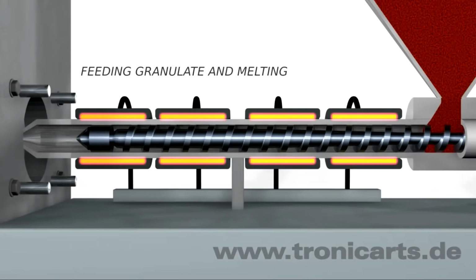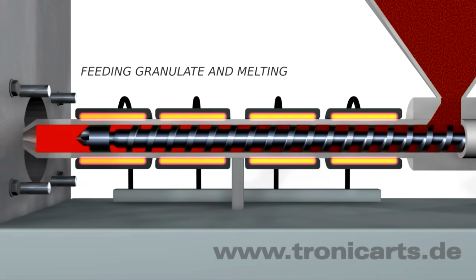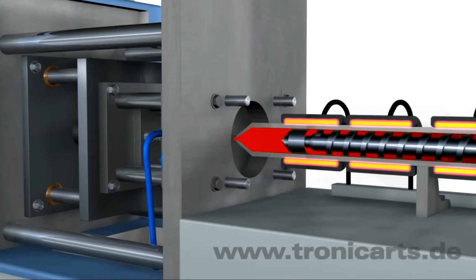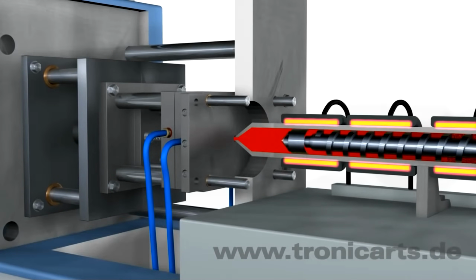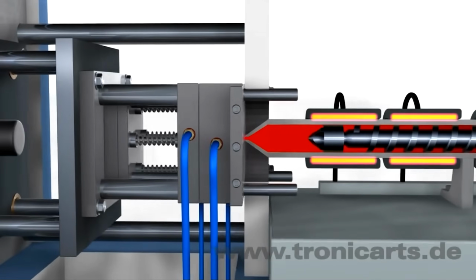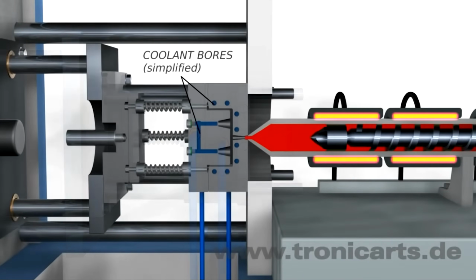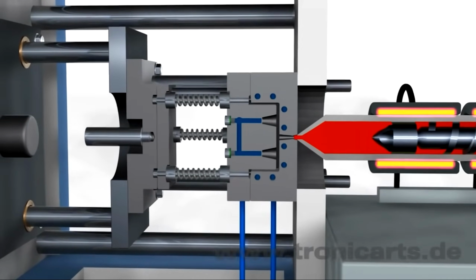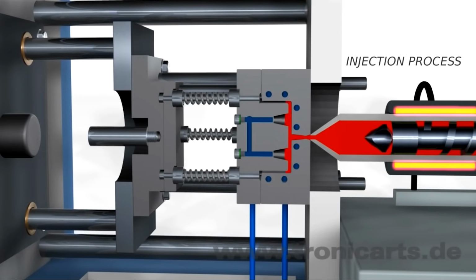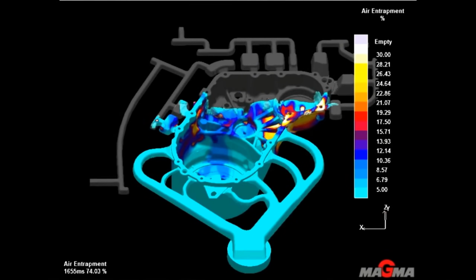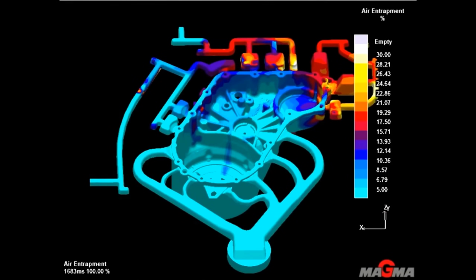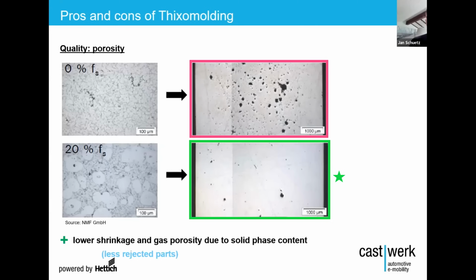Second, what about quality? The chip casting that Idra refers to is a thixomolding process, where magnesium chips are fed into an auger. The auger is surrounded by heating elements that warm the chips until they're semi-solid, like the consistency of soft butter, before being injected into the die chamber. That butter-like consistency means that when it's injected into the die chamber, there's no turbulence like there is with the fully molten metal used for aluminum casting, which means fewer voids in the material, which in turn means higher part quality and consistency. Why does that matter?